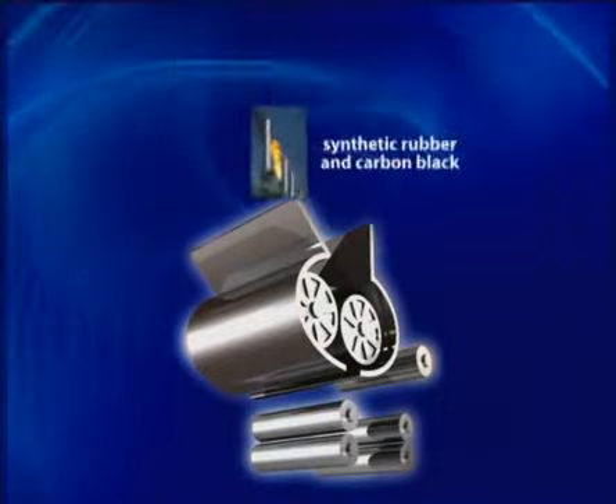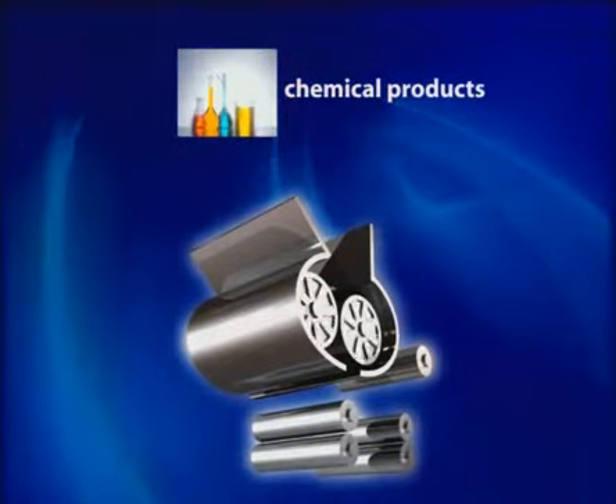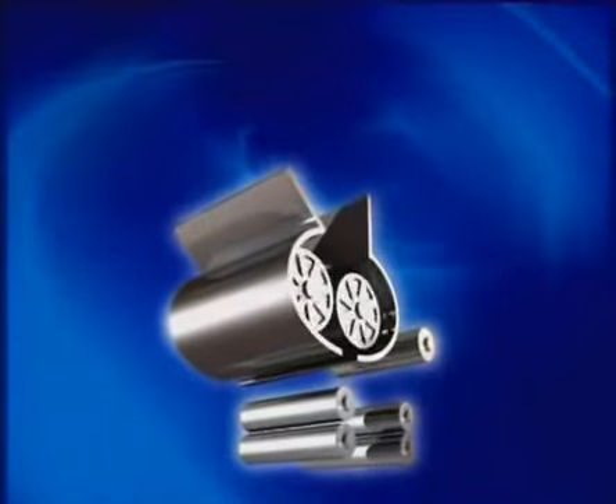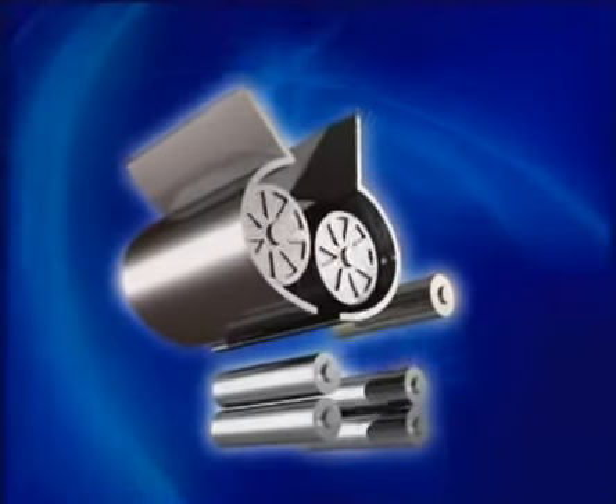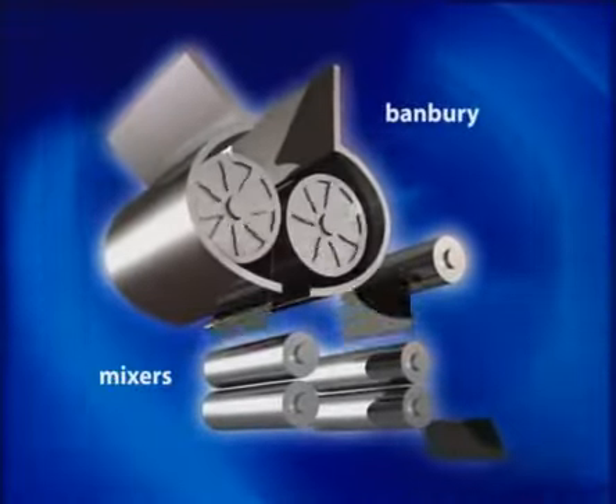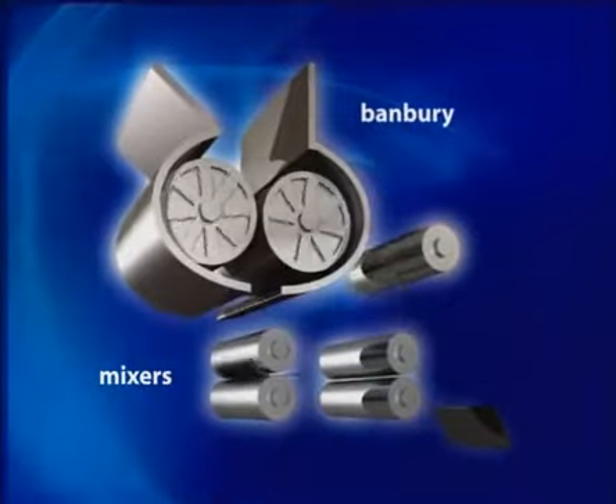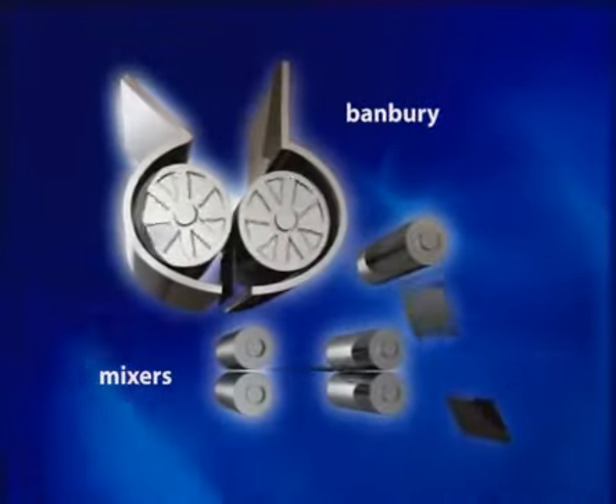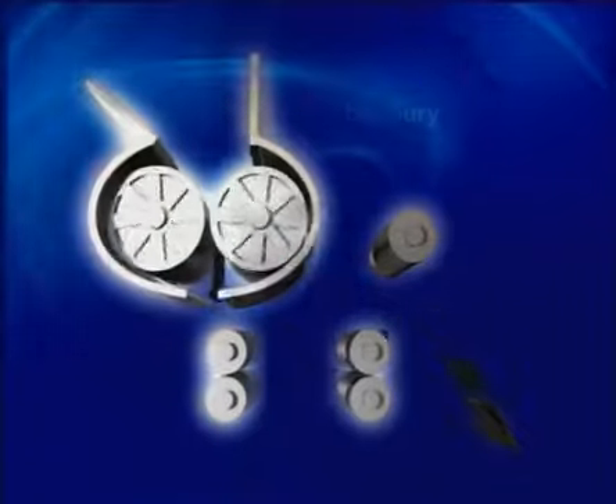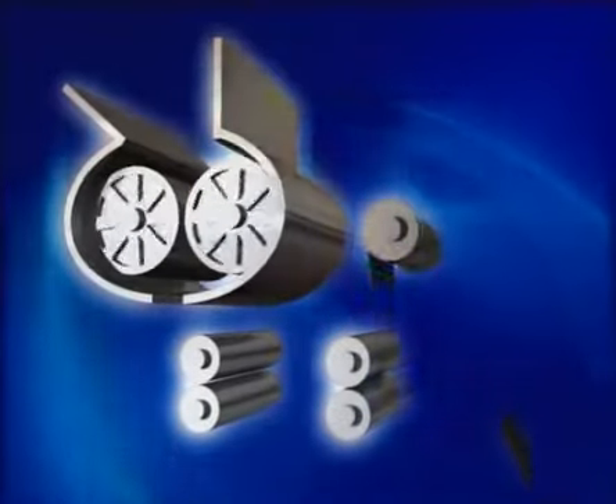The various ingredients in the proportions specified in the formula, which is naturally the most jealously guarded secret of each tire manufacturer, are put into a sort of mixing pot, the Banbury, where they are mixed by powerful motors and heated to a temperature of around 100 degrees. In a few minutes, the compound is ready to be used for the next processing stages. We'll now move back to the factory to see what happens in reality.